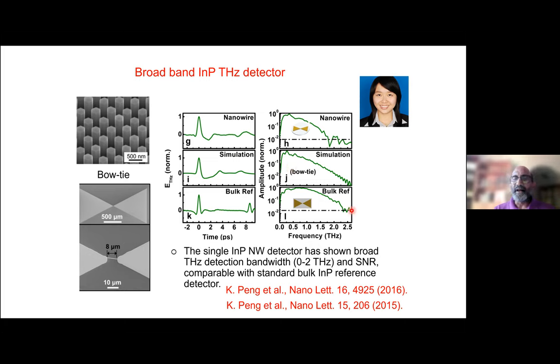And then again, you can see the bulk reference terahertz detector has a very broad bandwidth, and our nanowire detector also has a similar bandwidth, indicating that despite the small dimensions of these nanowire structures, we're able to get an excellent signal to noise ratio. These are the bow-ties here. In fact, the nanowire is just connecting these two antennas, because terahertz radiation is about 300 microns in wavelength. You want to couple that light into these nanowires, which are about 200 or 300 nanometers in diameter and a few microns long or so.